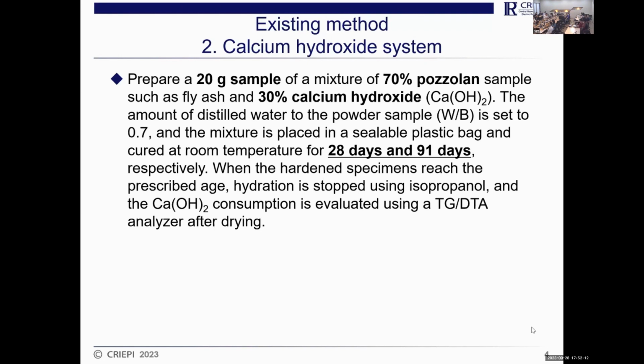And the second one is like this, using calcium hydroxide, and we mixed 20 grams of samples. In that, 70% is pozzolan, like fly ash, and the other 30% is calcium hydroxide. And we need to cure about 28 days and 91 days for the paste specimens. And after that, we determine the consumption amount of calcium hydroxide by TG-DTA, like so.